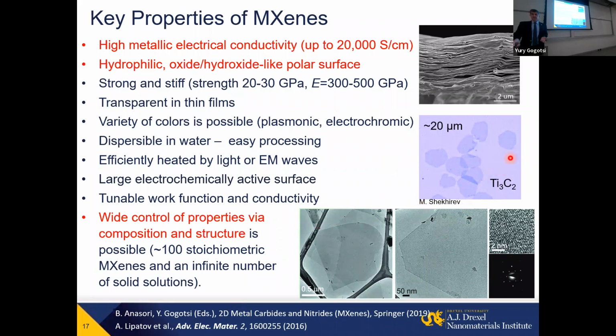This is an optical image on a SiO2 layer, a silicon wafer with a SiO2 layer. But if you look in TEM, you will see single layer flakes. You see this one is hanging in a hole of a grid. Again, something graphene won't be able to do. And there are single crystals. You can see it from high resolution TEM and selected area electron diffraction. But there are many other properties.